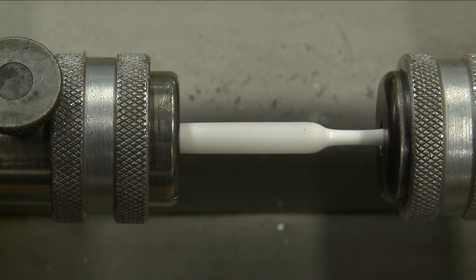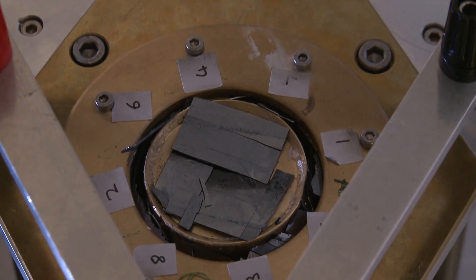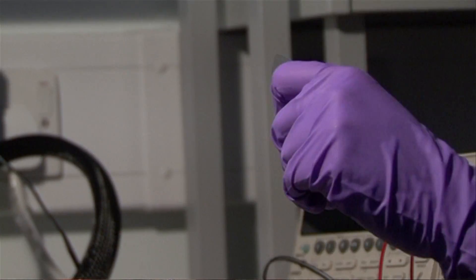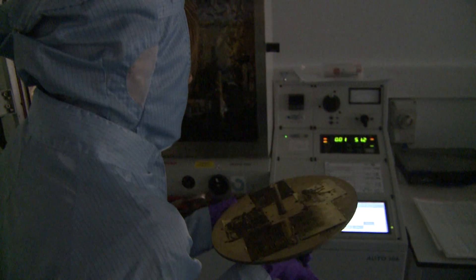The materials we use have some severe limitations. Push things too far, they break. But nanoresearchers are discovering ways around these limitations. Electronics is made out of silicon, and silicon is not very stretchy. But we found a way to make electronics stretchy. When you put a really thin layer of gold onto rubber and you stretch the rubber, we found that the gold doesn't break. This is because when gold is just a few nanometers thin, it forms cracks, and these cracks actually allow gold to stretch.